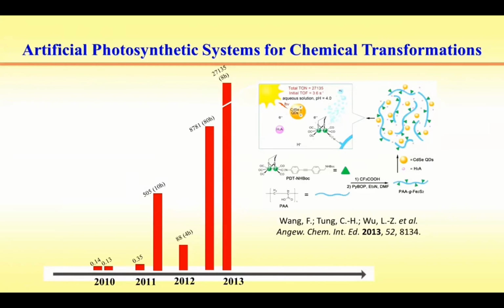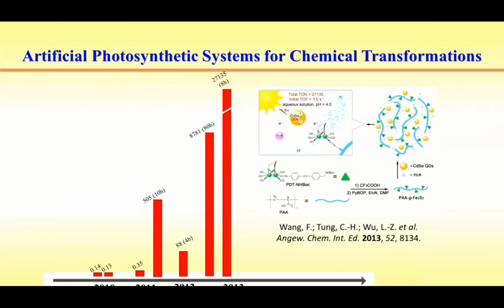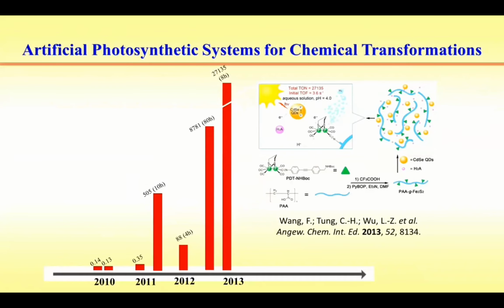The polymer chains, the assemblies, actually play three roles in these systems. It's a framework to bring the hydrogenase active site into aqueous solution. It's a good stabilizer, protecting the quantum dot from aggregation and enhancing the emission quantum yield of the photosensitizer. The most important thing is narrowing the distance between the photosensitizer and the hydrogenase mimics for efficient electron transfer. These three functions jointly contributed to the efficient photocatalytic hydrogen evolution.